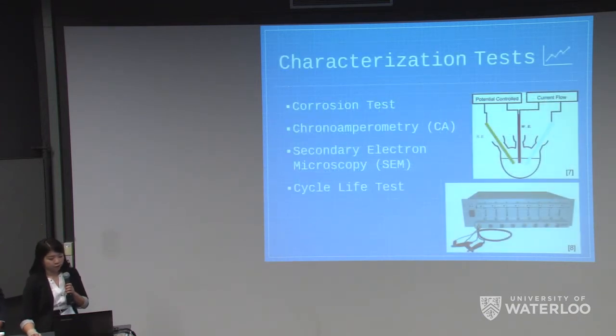So once the composition of the additives is decided, for the optimum gelling time, several characterization tests are also performed to study the key aspects mentioned earlier in the previous slide, including corrosion test, chronoamperometry, scanning electron microscopy, and cycle life test. Corrosion test is done to obtain the degree of corrosion on the electrodes, while CA and SEM are used to determine the amount of dendrite growth.